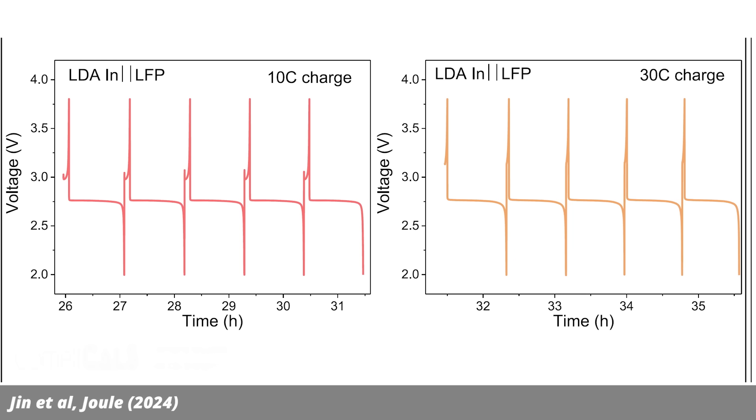In their tests, the researchers were able to charge the battery in about two minutes and show stability in over 1000 cycles. Now, they sound quite promising, but there are a lot of ifs and buts.